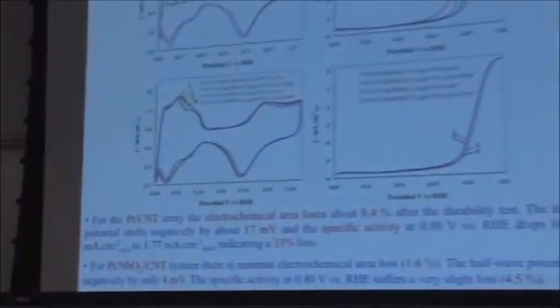So again, for commercial catalysts, after 10,000 cycles you lose more than 50% of your electroactive area. This is platinum with amorphous carbon. If we look at platinum on carbon nanotubes, you lose, in a reasonable voltage window but not the most extreme, 0.6 to 1.1, 8.4% electrochemical surface area, the half-wave potential shifts by 17 millivolts, and your specific activity drops by 33%.